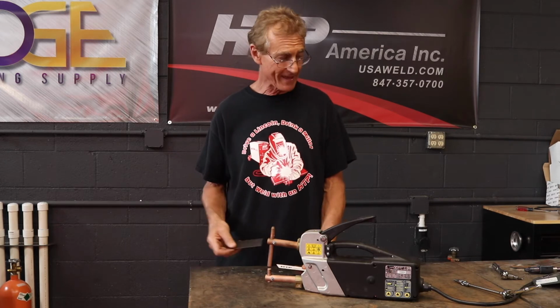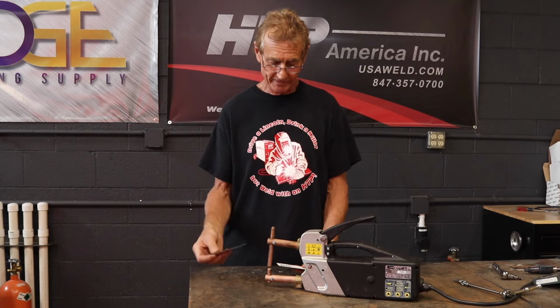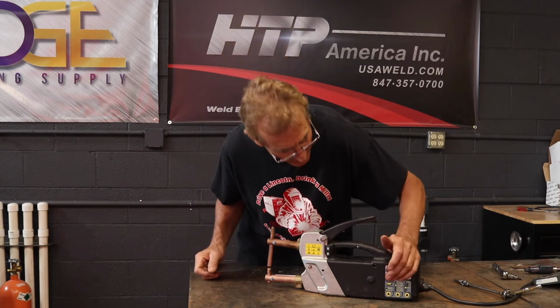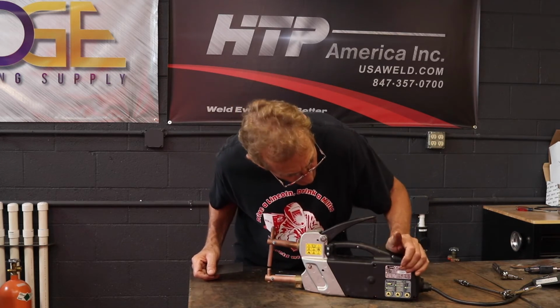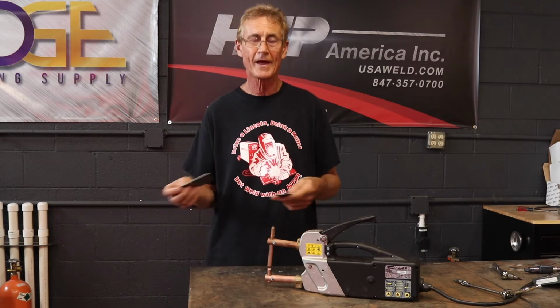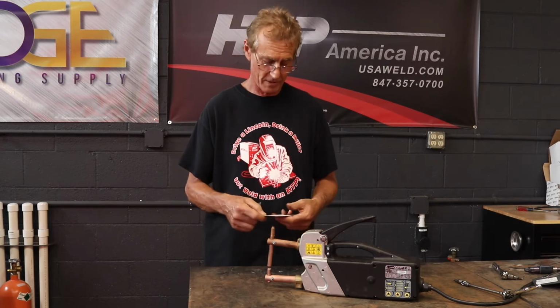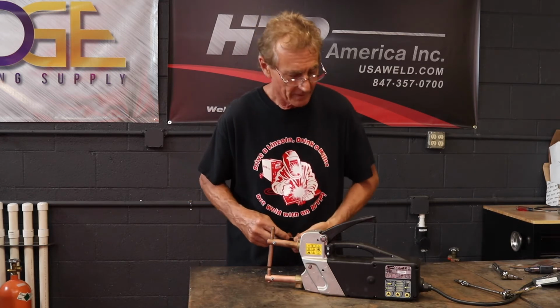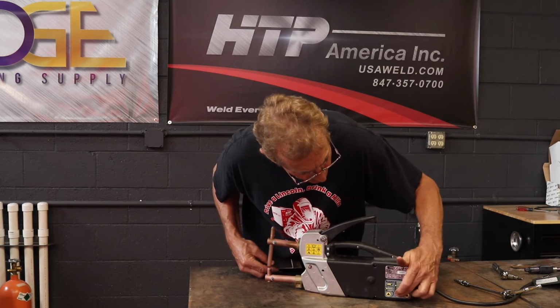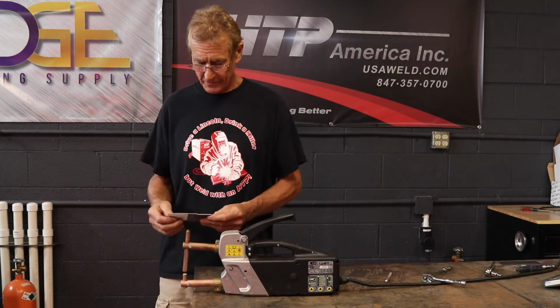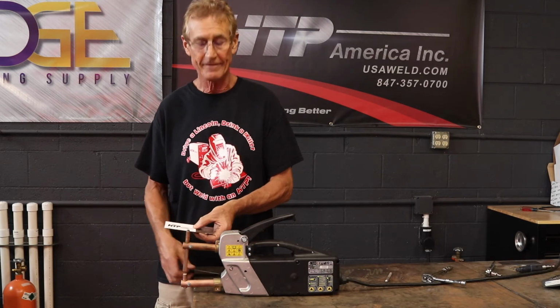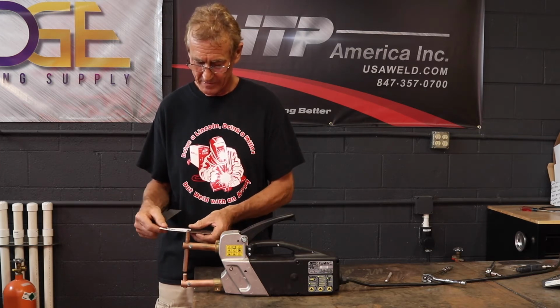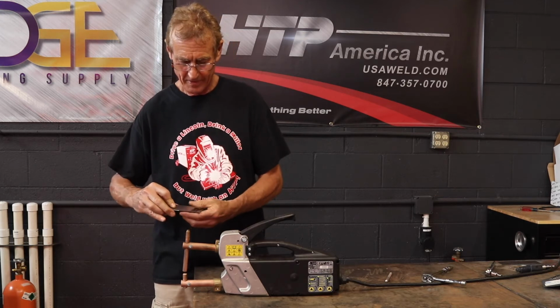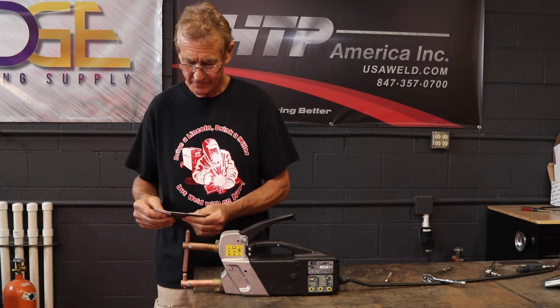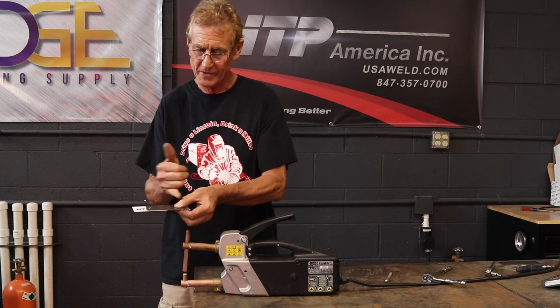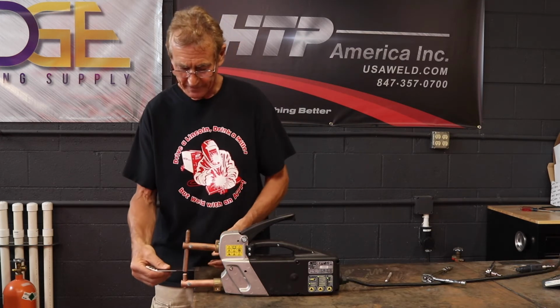So in the instance we had an E-coated panel, and we didn't want to remove the E-coating, we want to burn through it. A way we would trick the system is, I'm going to put it in the pulse weld mode. Now normally, since this is 1.5 and 1.5, and I'm going to try and weld through a business card, I am going to increase my thickness to 2 plus 2. So what I'm going to do is I'm only going to insert my business card over half of the panel to be an insulator, and then I'm going to leave this area from here back that I would be able to put a weld into.